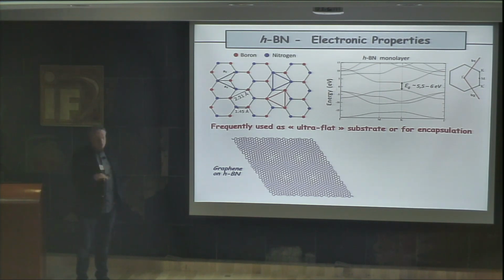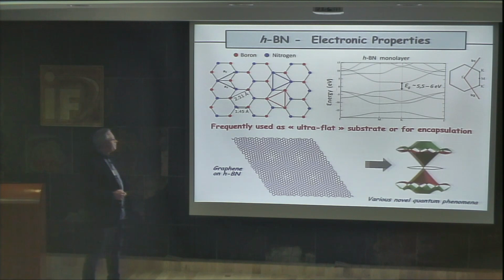Okay, so this 2D insulator material is frequently used, either in bulk or in few layers, as a substrate for graphene. Because graphene, when you put it on, for example, SiO2, is corrugated and induces some electron and hole puddles in the structure, which induce some scattering in fact in the transport properties of graphene. But when you put graphene on this ultra-flat substrate, you have extremely high mobility for your charge carriers, at least one order of magnitude compared to what you can obtain, for example, in SiO2.